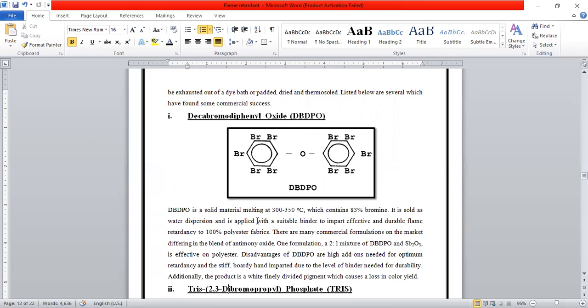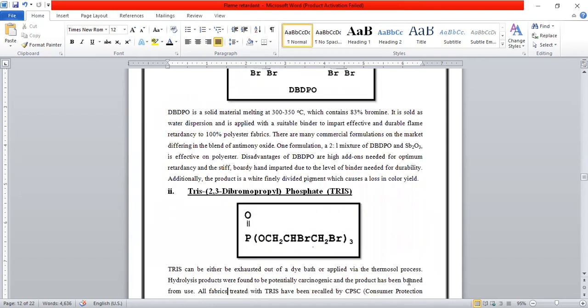One formulation, a 2:1 mixture of decabromodiphenyl oxide and antimony trioxide, is effective on polyester. Disadvantages of DB-DPO are the high add-ons needed for optimum retardancy and the stiff, boardy hand imparted due to the level of binder needed for durability. Additionally, the product is a white finely divided pigment which causes a loss in color yield.